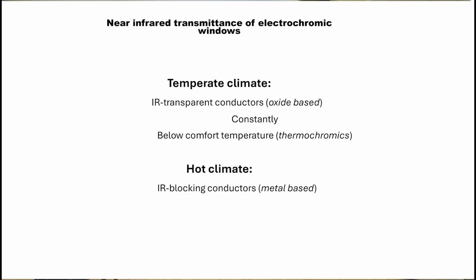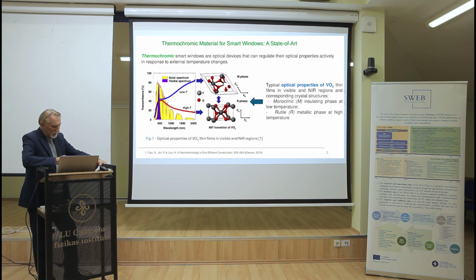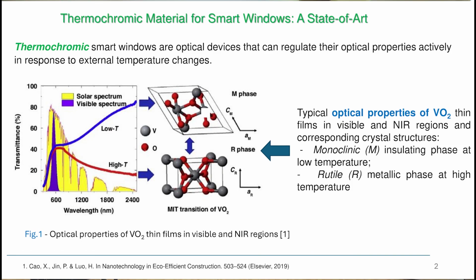And the last topic, which will also be presented by my colleague, Dr. Boris Polyakov, is about thermochromic materials, which are more sensitive to temperature and change in the infrared part of the solar spectra. As I have demonstrated from this paper, it is about a thin film of vanadium dioxide. You see that in the visible part, these spectra practically don't change with changing temperature, but in the infrared, we can change completely. You can block the infrared part, and so you can significantly decrease the flux of heat through the window.